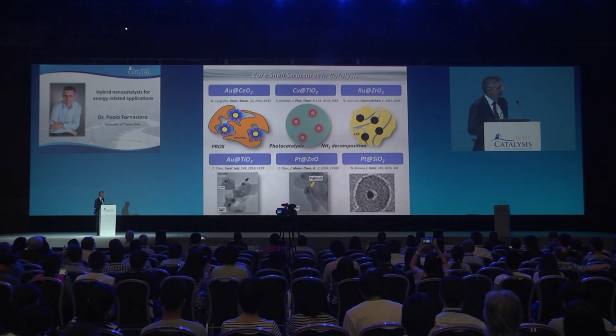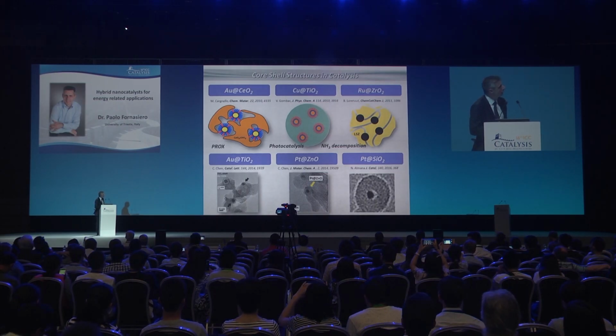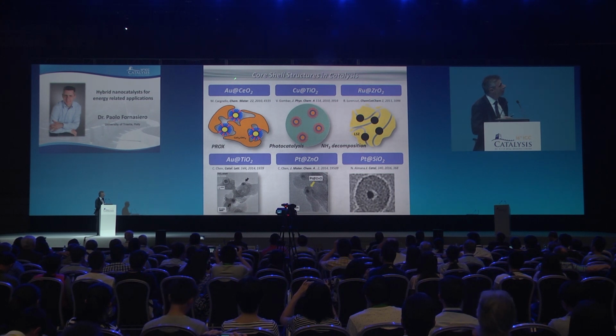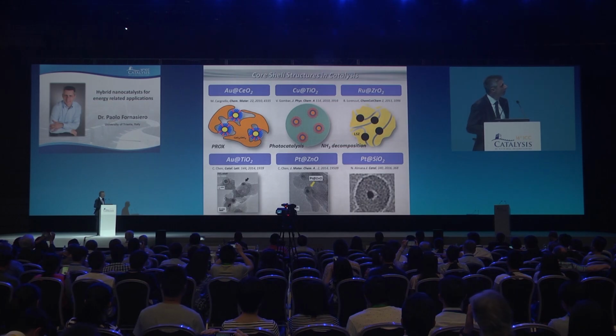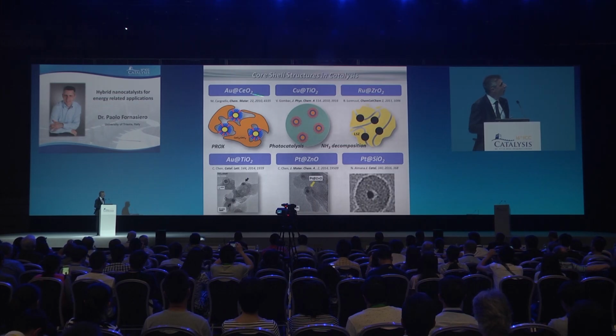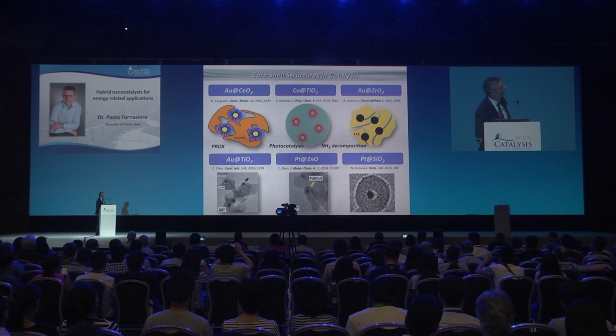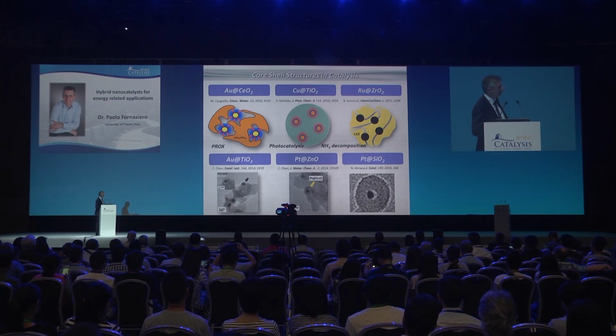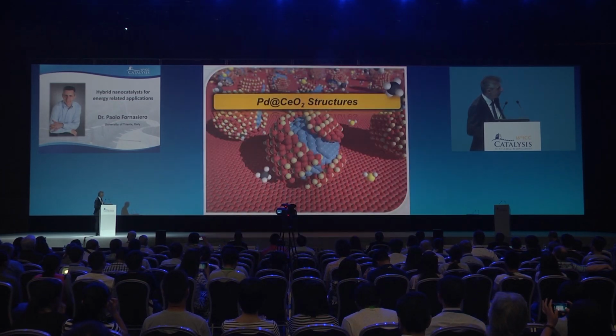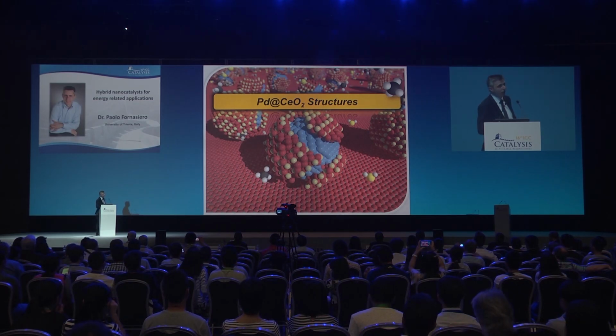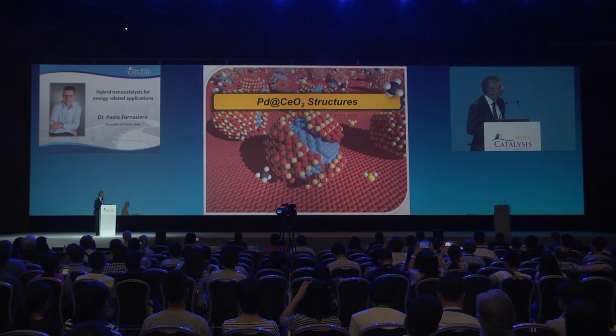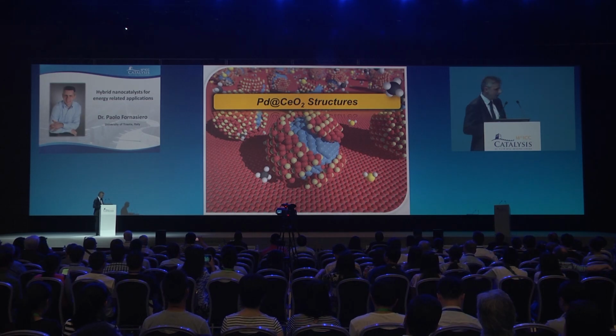We have proved in the last couple of years that this is a general methodology to make different types of catalysts, changing the metal: platinum, gold, copper, ruthenium, even rhodium, and different types of oxide: ceria, titania, zirconia, all work, up to just a couple of days ago when it worked on platinum silica. And always we found improved activity or stability or selectivity. So let me show you some examples of what I do believe is a very elegant approach. And I'm going to talk about palladium at ceria structures.